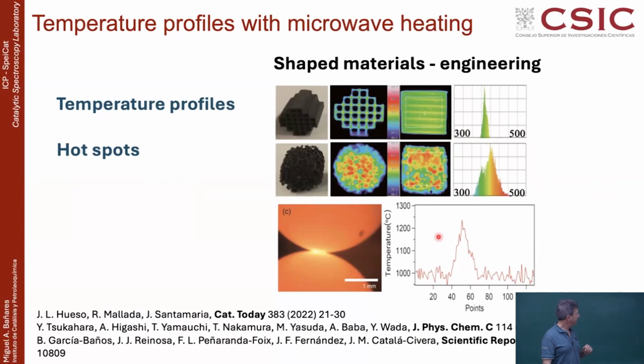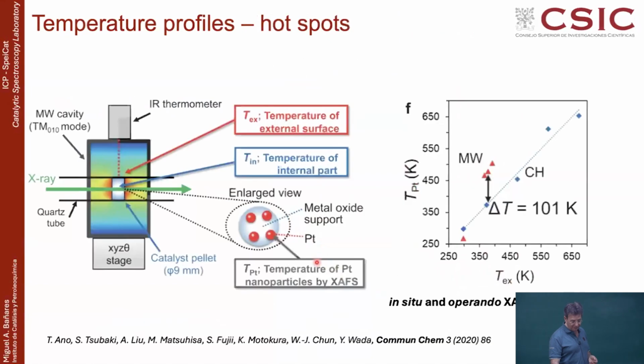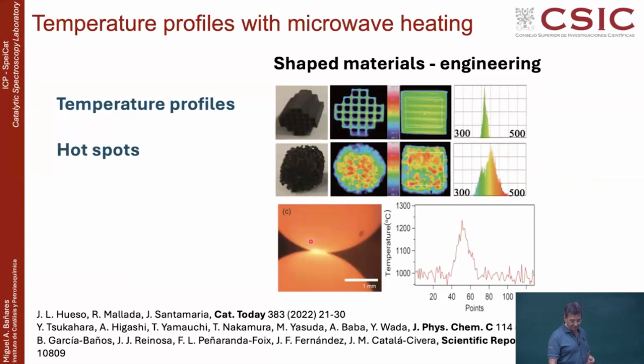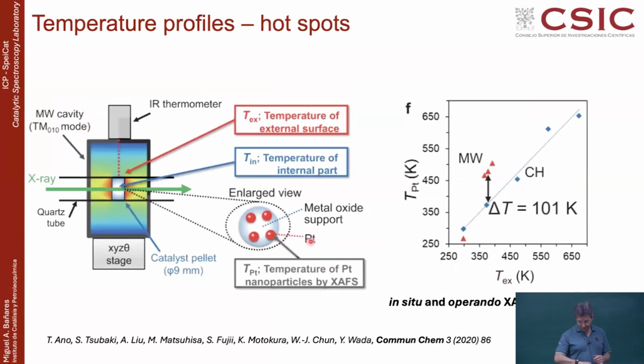But anyhow, the other challenge is when you want to go to industrial catalysis, you are not dealing with a powder, you are dealing with a shaped catalyst. A shaped catalyst can have the shape, for instance, of a brick, a monolith, or can be a ring or whatever. So different kinds of pellets or different kinds of structures. And with this infrared camera, you can get the temperature profile within these particles or within this catalyst to better monitor what is the temperature profile and how they are behaving, or even if there are hot spots in the system of these materials. So this is a part of the challenge.